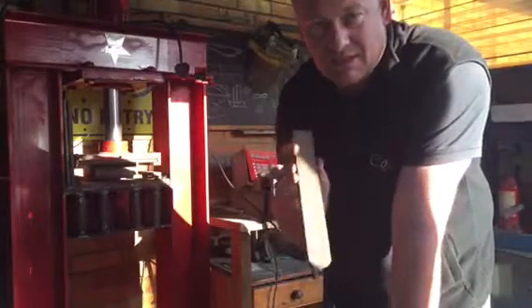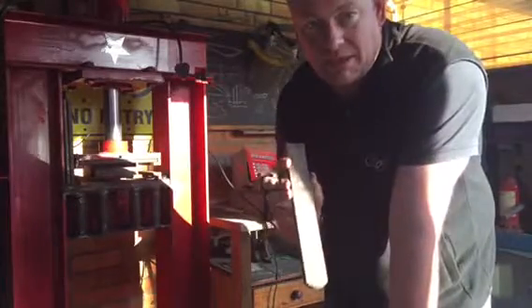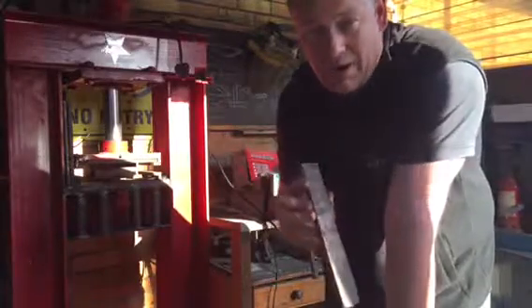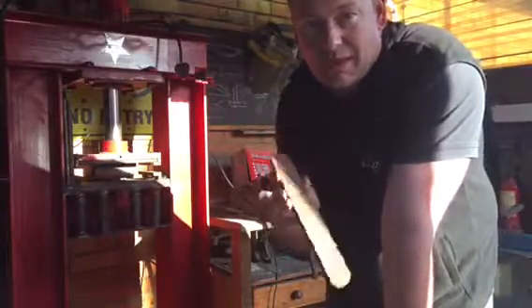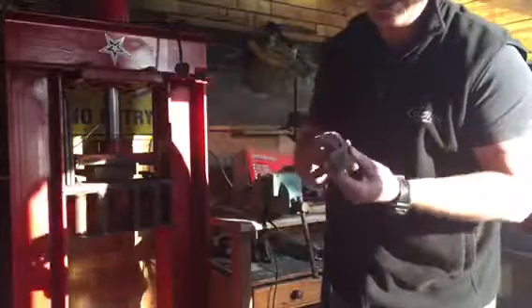This is called fire scale, so it's very hard, about 65 Rockwell and up. Any disc that can grind this stuff off is quite a tough disc. The thin one mil disc worked very well in cutting through the billets to get into smaller pieces like this. They were then restacked and forged again to make a bigger bar, drawn out like this.